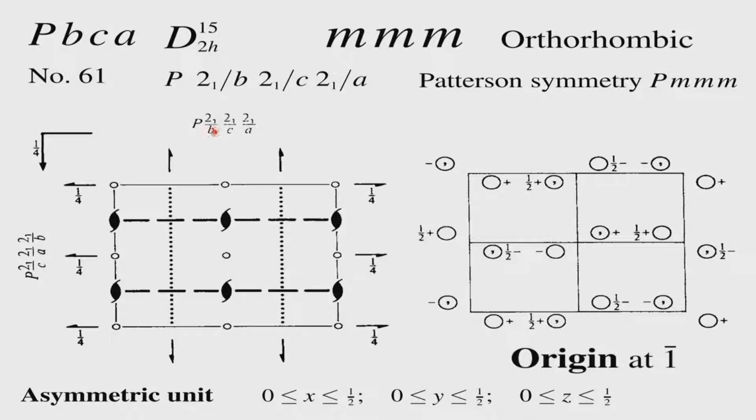And therefore, I have considered the monoclinic, triclinic and orthorhombic systems. Among these, I have considered only the most commonly occurring systems. We discussed P21/C as the most commonly occurring centrosymmetric monoclinic system. The non-centrosymmetric P212121 in the orthorhombic case also occurs very often, and PBCA is its counterpart as far as center of symmetry involvement is concerned. So it is actually P21/B 21/C 21/A.